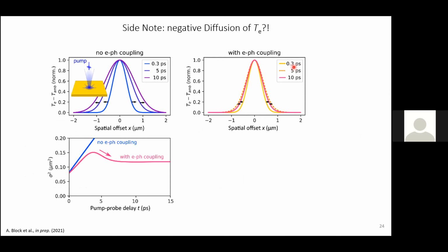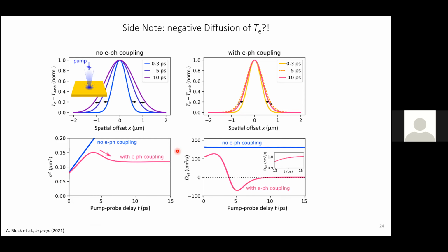So again, this full width over time goes up. In the end, it goes to 1, but in the middle, it actually decreases a little bit, which we thought was kind of interesting, especially if you think of what a negative heat diffusion is. That's heat contracting. That's not allowed by thermodynamics or something like that. But in this two-temperature regime, this absolutely does make sense.